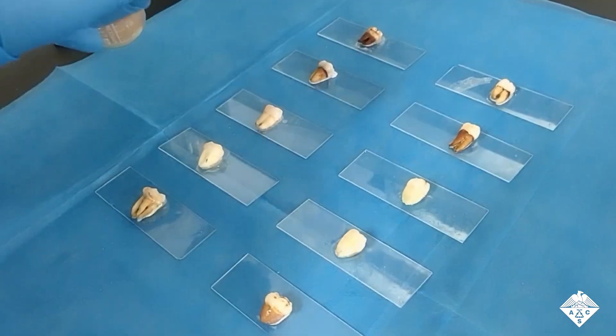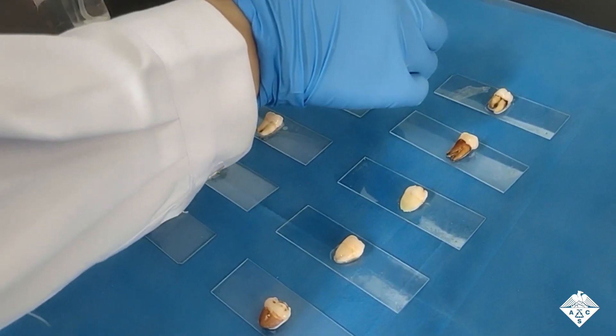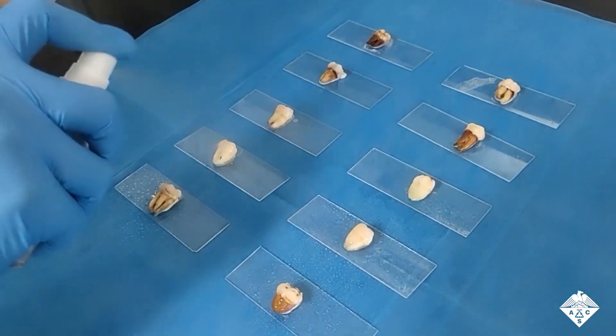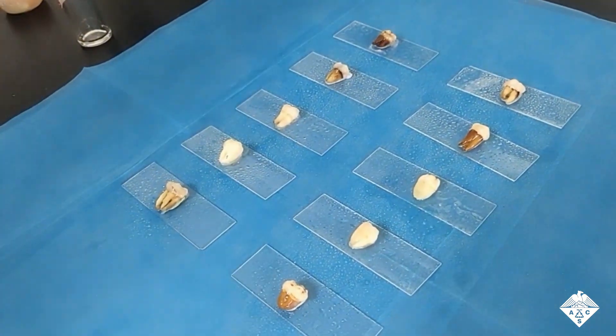The researchers combined bismuth oxychloride nanoparticles, copper oxide nanoparticles, and sodium alginate into a thick mixture. Then, they spread the mixture onto the surface of teeth stuck to slides, and sprayed them with a calcium chloride solution, forming a strongly adhering hydrogel.